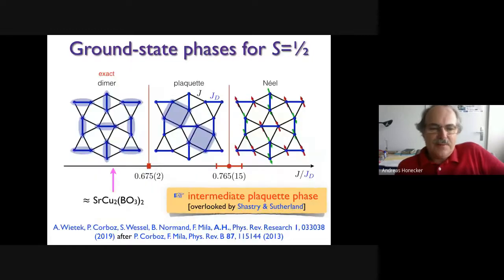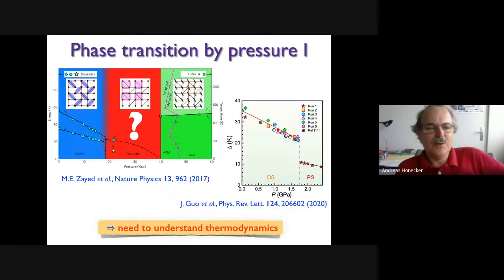Okay, now I forgot to insist that strontium copper borate is in the exact dimer state phase, but very close to the phase transition. And so if it is close to the phase transition, you might hope to drive it across the phase transition by applying, for example, pressure. And people have tried to do this. And here are some previous works. So here is an attempt.